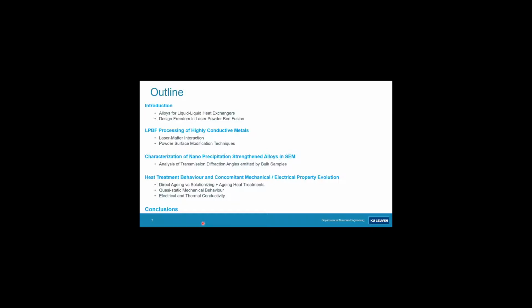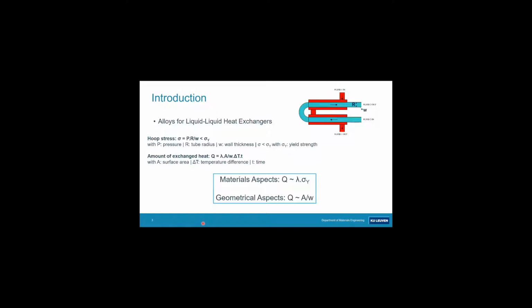And as you know, for metals, electrical and thermal conductivity go hand in hand. So this is actually an introductory slide which I use in one of my bachelor courses, where we try to explain students why they should look at material properties for a certain design. And this is for a tube-in-tube heat exchanger with two liquids flowing, so a cold and a hot liquid. And as you see here, the amount of heat which you can exchange is linearly dependent on the thermal conductivity of the material which separates the cold and the hot stream. And it's also linearly dependent on the yield strength of the material.